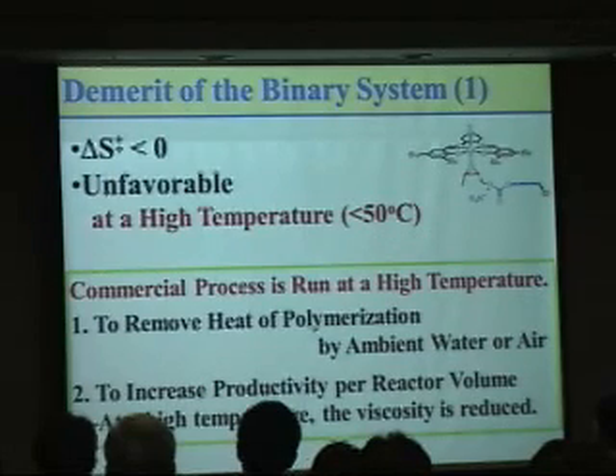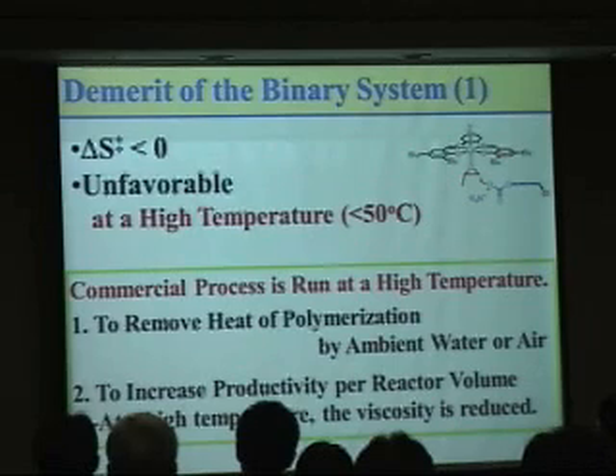All the commercial processes producing polymer are run at a high temperature. The polymerization reaction is an exothermic reaction. So in order to remove the heat of polymerization, we have to run the polymerization at a high temperature. And in bulk and solution polymerization, we get a very thick viscous polymerization solution, and the productivity per unit volume is governed by the viscosity. So at high temperature, the viscosity is typically reduced, so we can make much more polymer using the same size reactor.